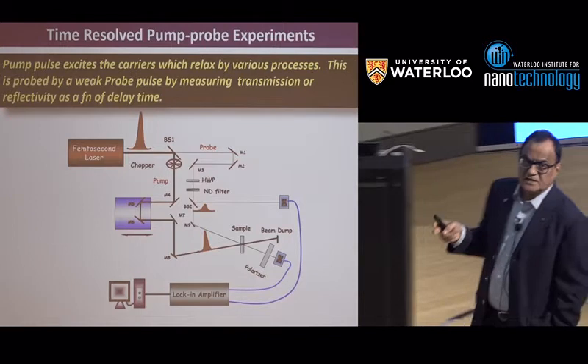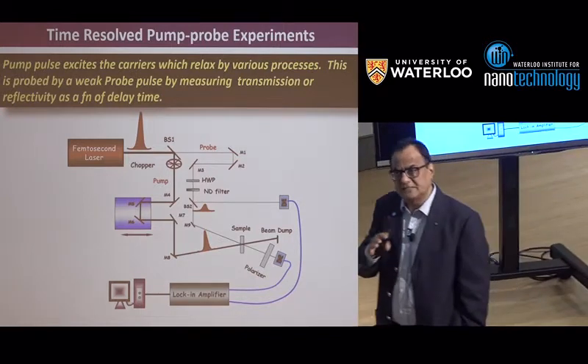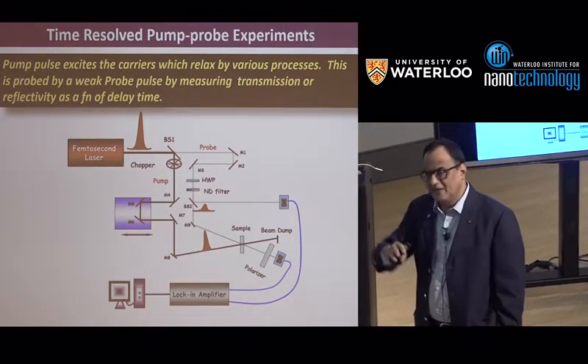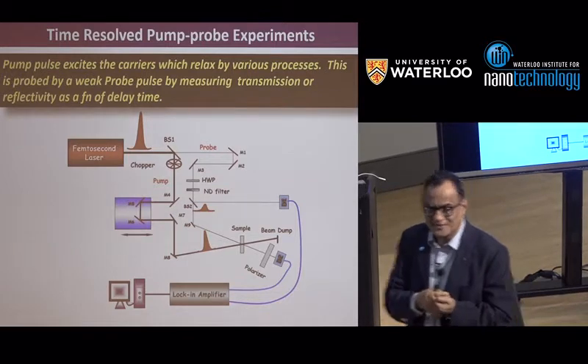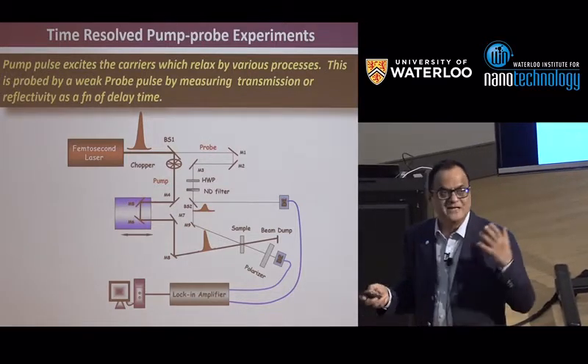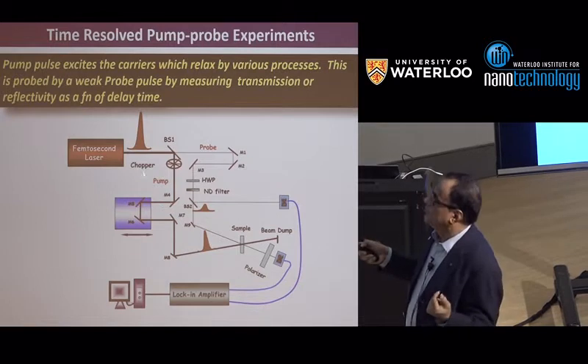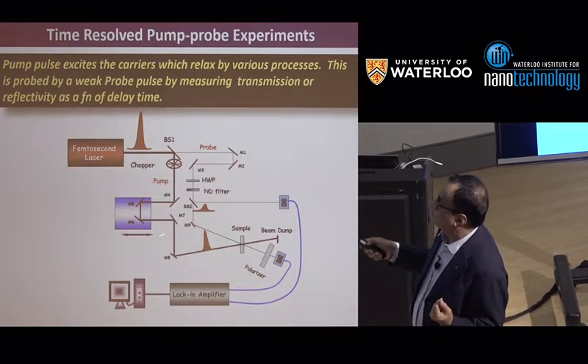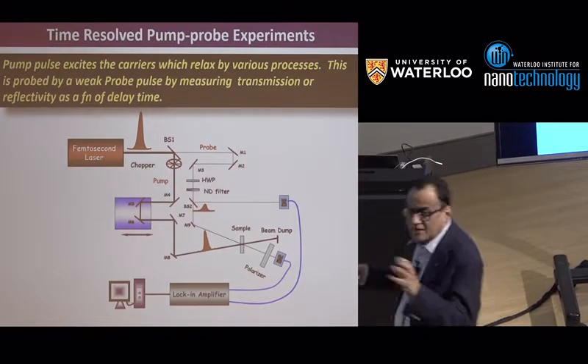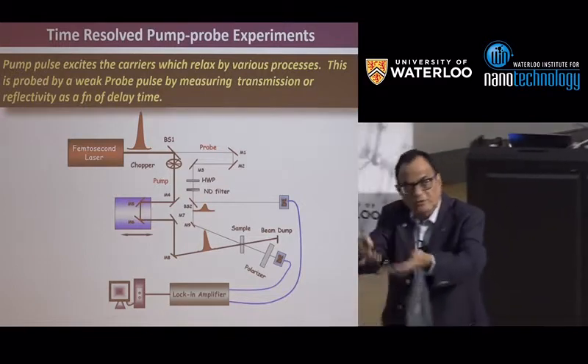So the experiment is very straightforward and simple. Simple, quote unquote, because it takes a while to set it up, but the idea is a pump probe experiment. Now you have a pump beam which can excite the sample, and what happens in the sample is a non-equilibrium state.